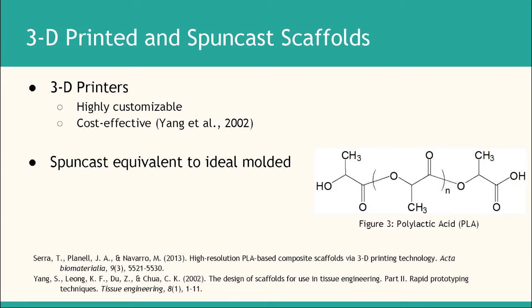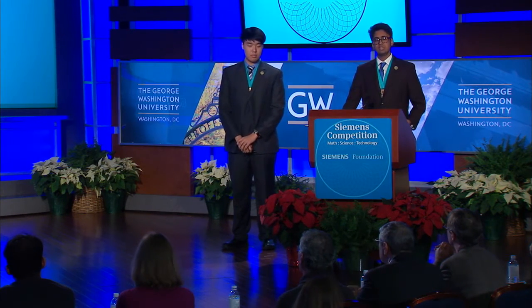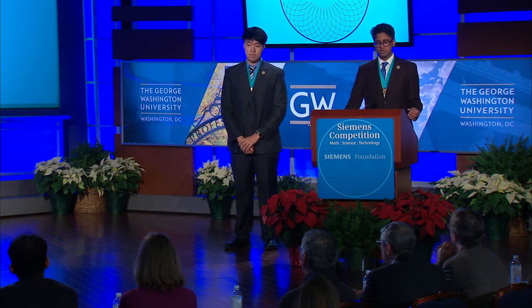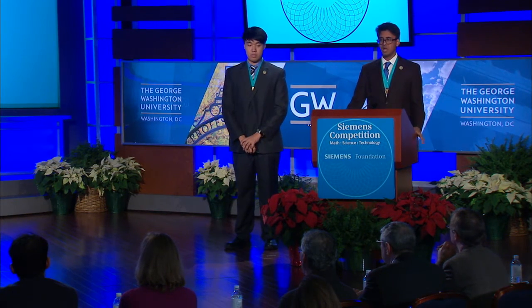We use spun cast scaffolds as equivalent to ideal molded scaffolds, as both are completely flat and have identical surface topographies. The FDA has been trying to give 510K pre-market approval to 3D printed structures, which states that the 3D printed structures are substantially equivalent to the legally marketed device, or molded scaffolds. We used a reproducibility test creating structures from two separate 3D printers to see whether they truly had identical surface topographies, and also whether 3D printed structures or spun cast scaffolds would show higher levels of proliferation or differentiation in vitro. Our two main objectives were to assess 510K approval and to assess proliferation and differentiation on 3D printed scaffolds.